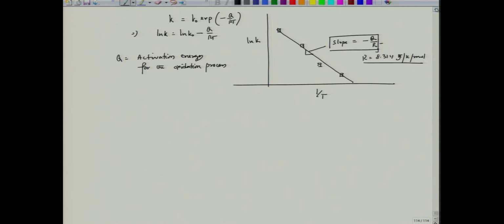So, now we could see that without understanding much of the mechanism of the process, at least I could get useful data for the isothermal treatment, isothermal oxidation operation. What are those useful data? One is, at a different temperature, what is the oxidation rate constant, and once we know the rate constant at at least 4 temperatures, we can do this kind of treatment and get the activation energy for that oxidation process.